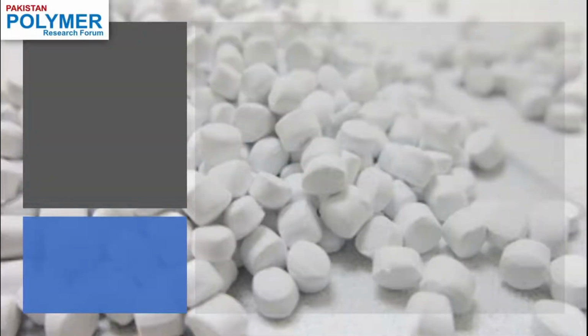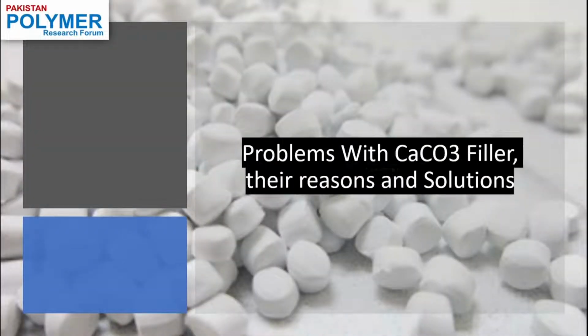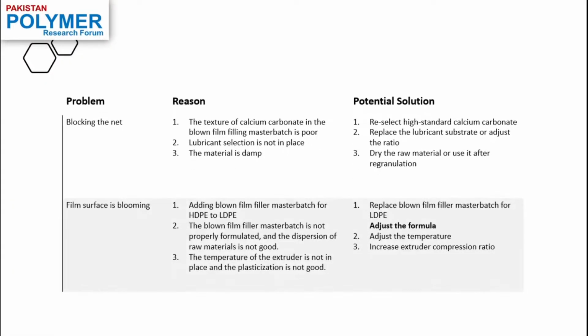Now we're coming to the main topic of our presentation, which is the problems that occur when we're using the calcium carbonate filler, the reasons for these problems, and the potential solutions that can be applied in a cost-effective way to reduce the problems with the calcium carbonate filler. The first problem that occurs is the blocking of the net. The blocking of the net actually means that when you're manufacturing the calcium carbonate filler master batch, you're using extruders and there are sieves at the end of the extruder, and our master batch has to pass through the sieves during the end stages of our extrusion process.